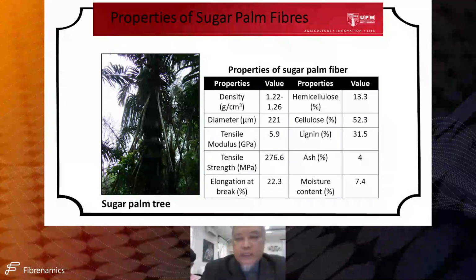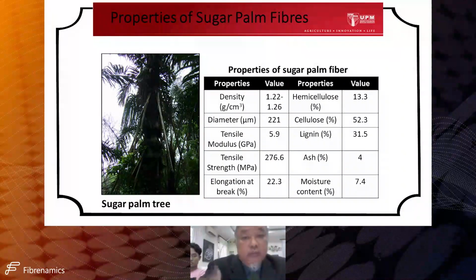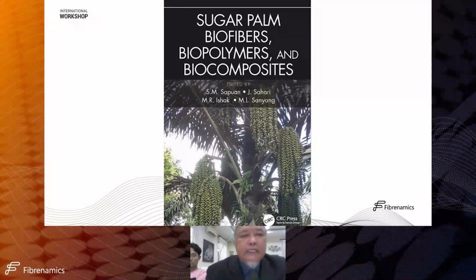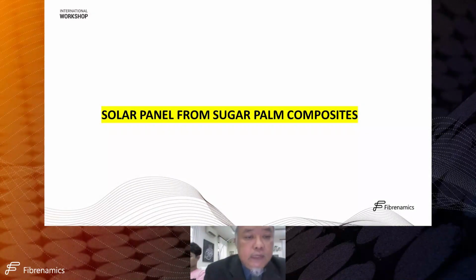Okay, on the property of sugar palm fiber, on the left-hand side, the tensile modulus is 5.9, tensile strength 276.6. To me, that is quite good, because the fiber from this plant has been used in the past, like in the Sultanate of Malacca. They used it to make small boats. Even during the time of the British in Malaysia, they used it as ship cordage. So this fiber has a very good quality, and for instance, durability: the longer you soak it inside the water, the better the properties. It's quite amazing. So that's why we believe this plant has so much potential, and we managed to publish with CRC Press books dedicated to that fiber and biopolymers from the sugar palm plant. Okay, one of the products recently that we developed is a solar panel from sugar palm.